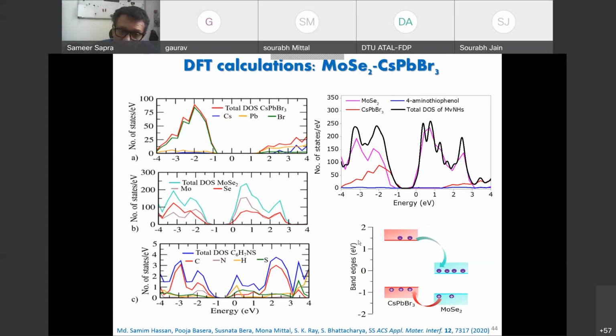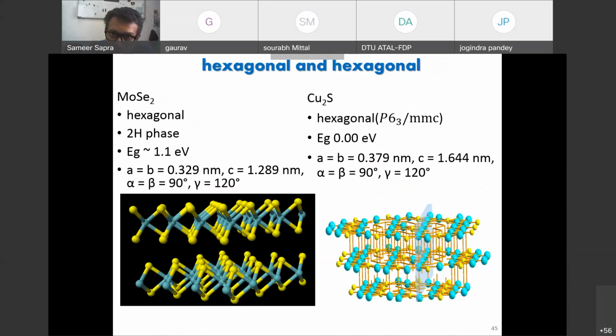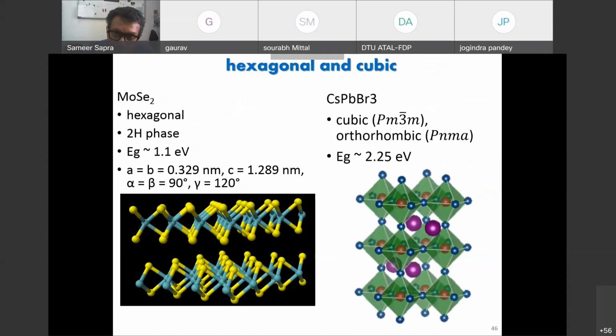Okay. Well, Shashwata went ahead and calculated some more heterostructures since we were working on cesium lead bromide. And again, this is all the DOS, and essentially focus here. He says that again, look, this is a type 2 heterostructure. But to make it experimentally, MoSe2 and Cu2S were both hexagonal, so we could do it. If you look at cesium lead bromide, then it's a cubic structure. And how does one make a heterostructure of MoSe2, which is hexagonal, with a cubic one? There's a lot of mismatch.